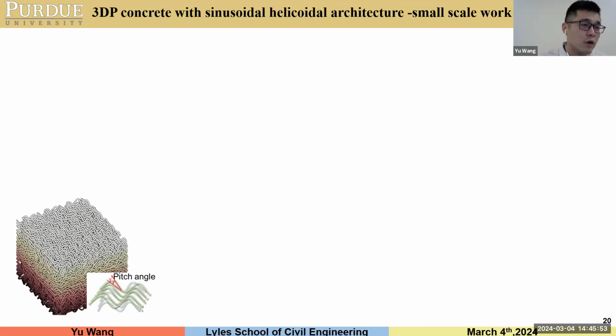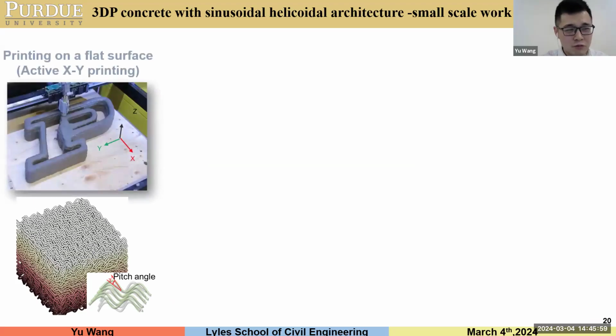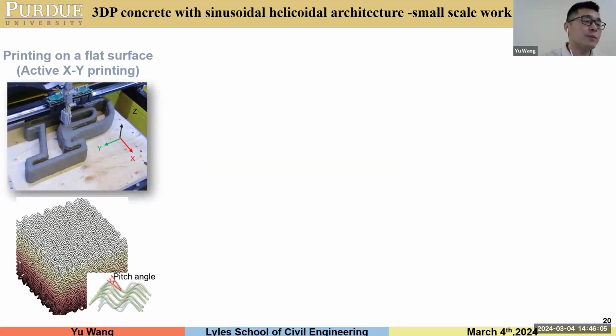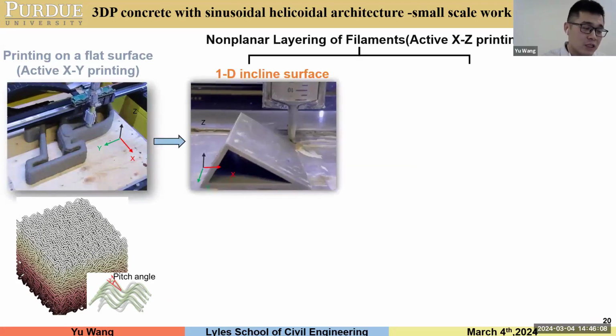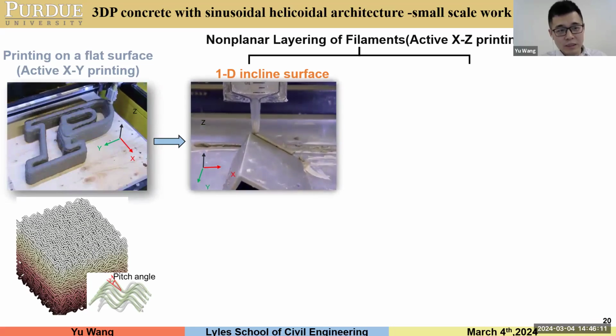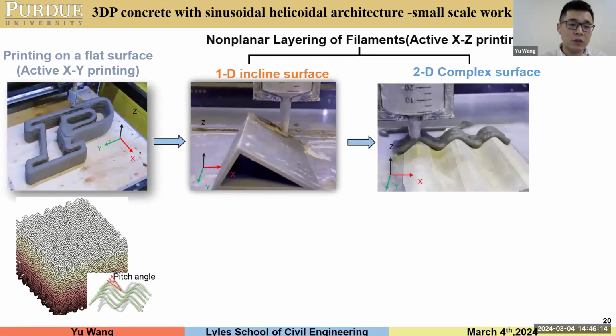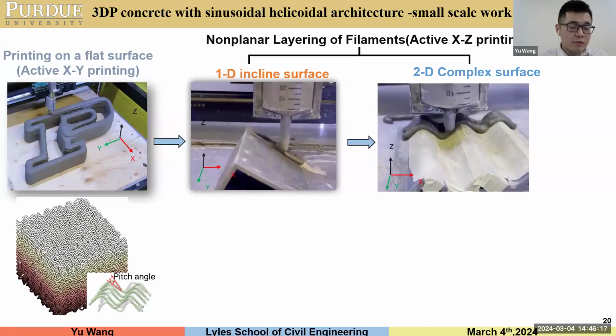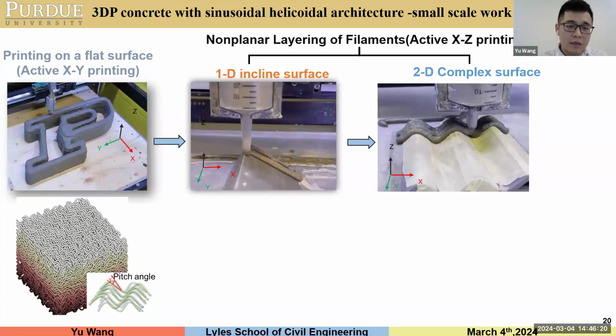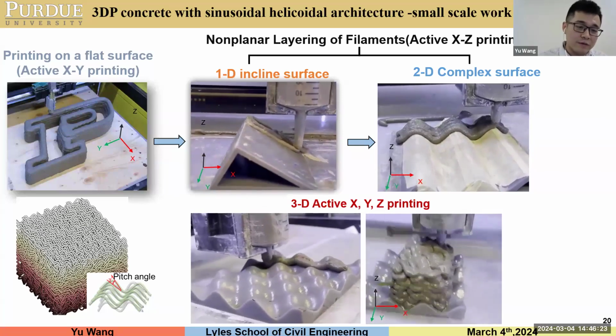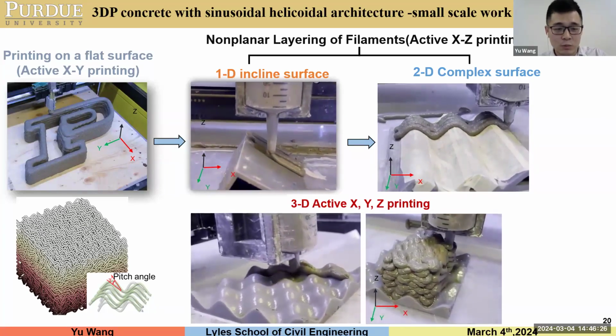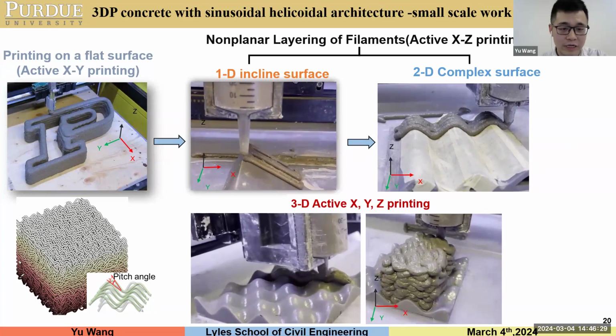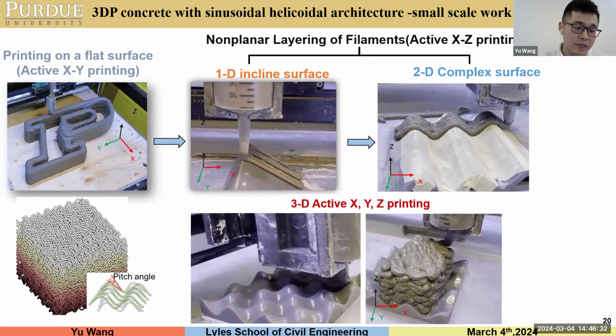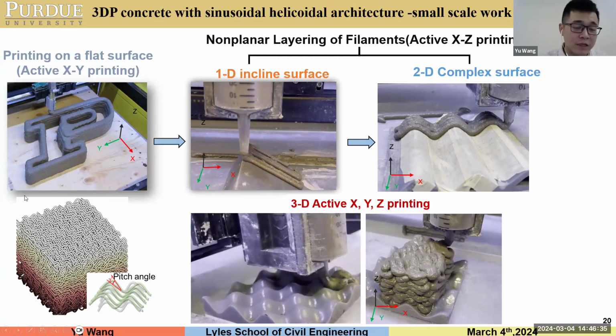The other architecture we also started to look at in small scale is the helicoidal architecture. This is relatively new in 3D printing concrete, because typically when we print concrete, we print in the X and Y plane and build up in the Z direction. For this architecture, we need to study how to print on a 1D surface, and then scale it to a sinusoidal surface to achieve the filament shape of this architecture. Then we scale this to a 3D surface, where we actively print in X, Y and Z with the sinusoidal architecture and with the rotation of each layer, to make it really closer to the real structure found in nature.